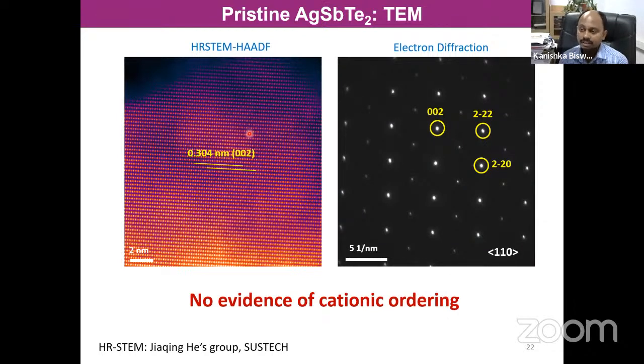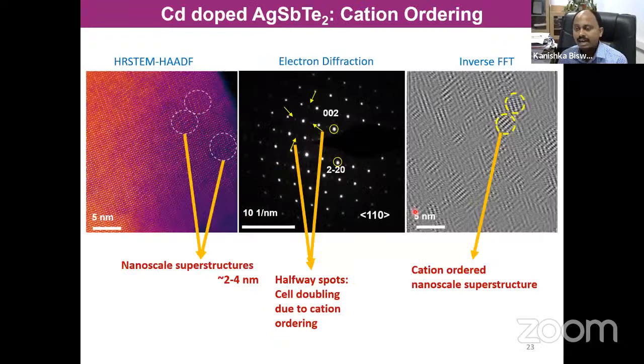Now, if I do more crystallography, this is the electron diffraction pattern from this region. You can see the fundamental spots are due to the sodium chloride structure, the disordered structure. We don't see any superstructure spots, because a superstructure is the indication of ordering, which can create supercells in this compound. Then we have done it for cadmium doped AgSbTe2. You can see there is an intensity distribution inside this circle, and the circle size is basically 2 to 4 nanometers, which forms endotaxial type nanoscale superstructures. This is cadmium doping causing silver and antimony ordering on a very local scale. So this is not the global scale ordering which we wanted. And the electron diffraction or crystallography tells you, the yellow arrow you can see.